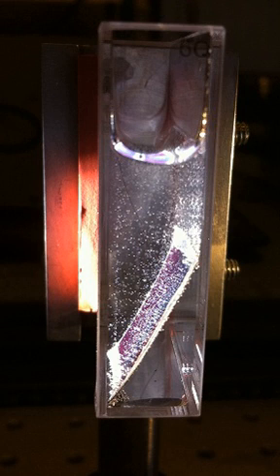Gion Calzaferri, 2009, describes one such antenna that uses zeolite L as a host for organic dyes, to mimic plants' light-collecting systems. The antenna is fabricated by inserting dye molecules into the channels of zeolite L. The insertion process, which takes place under vacuum and at high temperature conditions, is made possible by the cooperative vibrational motion of the zeolite framework and of the dye molecules. The resulting material may be interfaced to an external device via a stopcock intermediate.